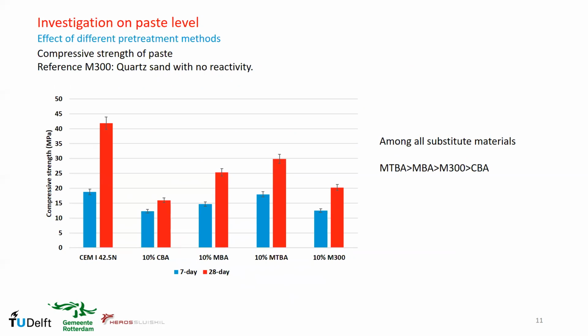Then further investigation at the paste level to check the effect of different treatments. First, the compressive strength of hardened paste at 7 and 28 days with a fixed replacement ratio of 10%. Here we select M300, which is a micro quartz sand with no reactivity, used as a filler substitute in Portland cement. Among all of the substitute materials, we found the highest compressive strength is with 10% of MTBA, higher than MBA, followed by M300 and CBA with the lowest compressive strength.